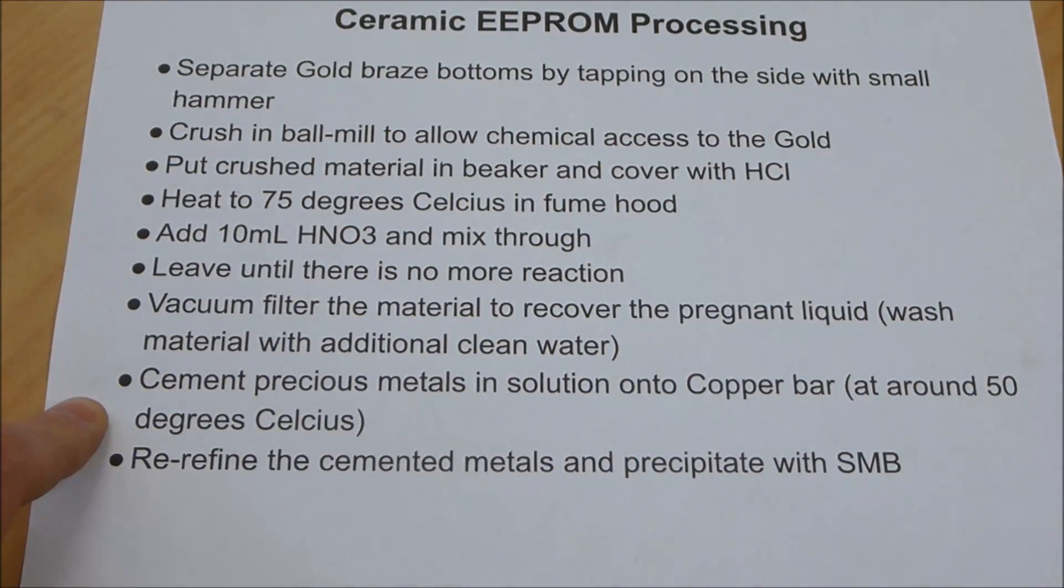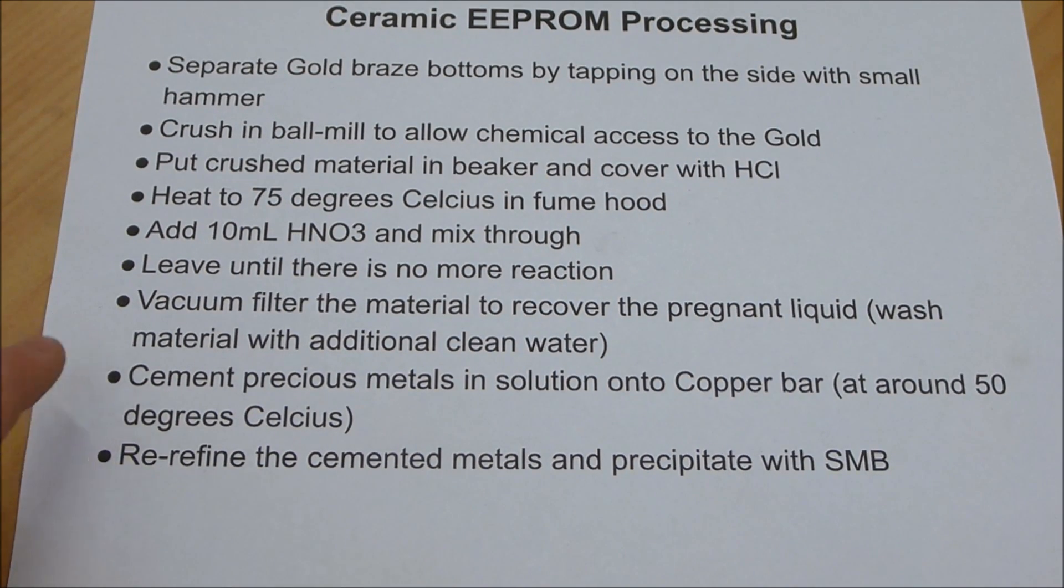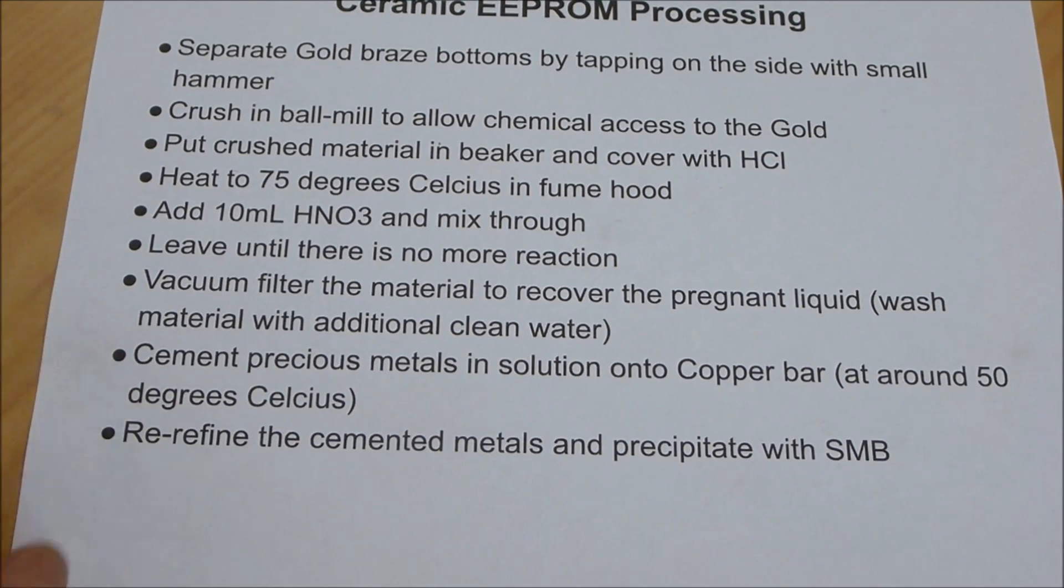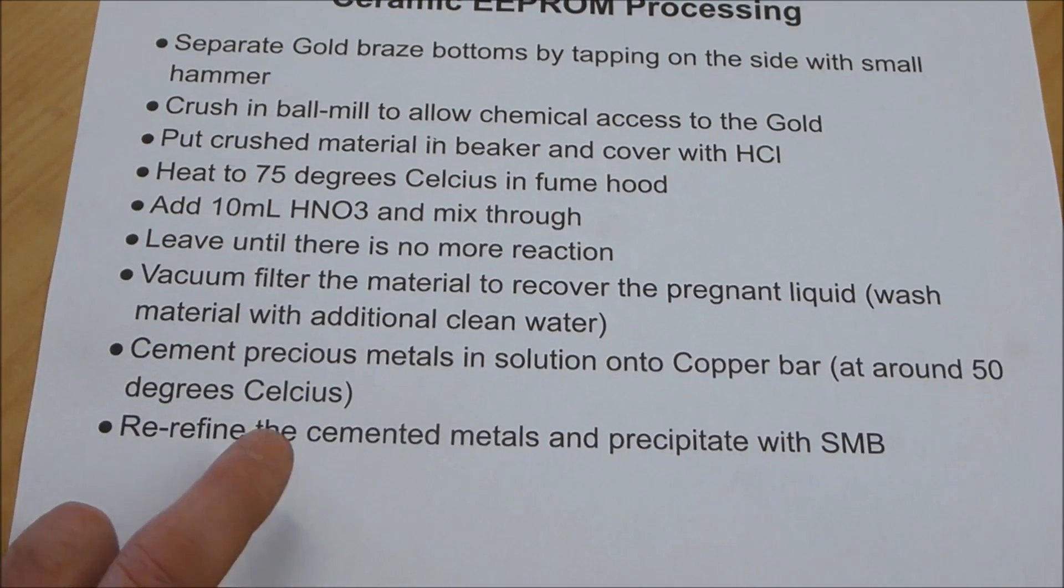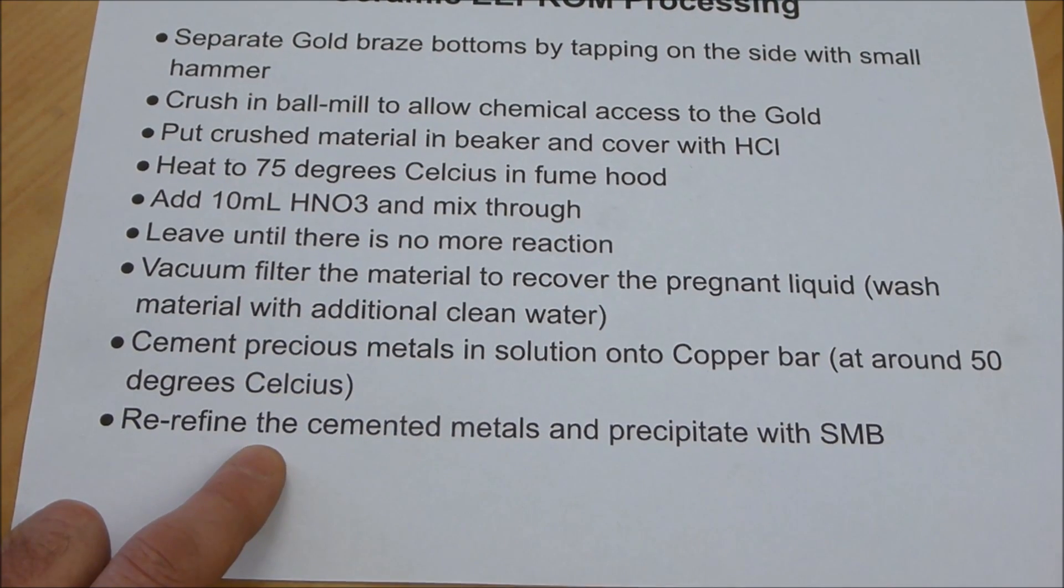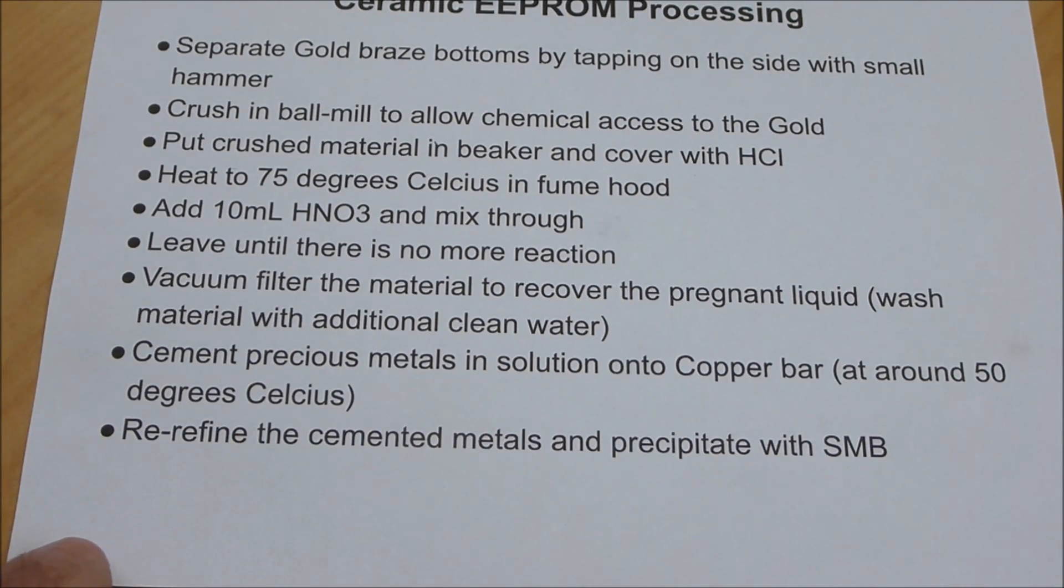The reason I do this is because there is still quite an excess of nitric acid present. Cementing on a copper bar takes care of that problem at the same time as cementing out all the gold. Then after a couple of hours when all the gold is out of solution, I will just basically do a very simple re-refine with aqua regia and precipitate with sodium metabisulfite.